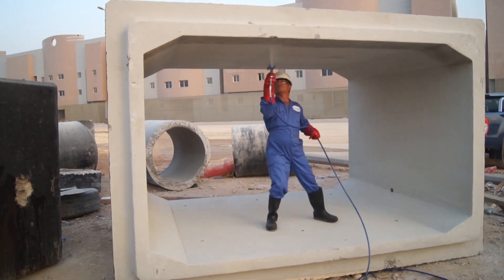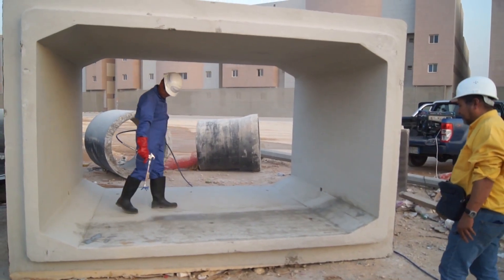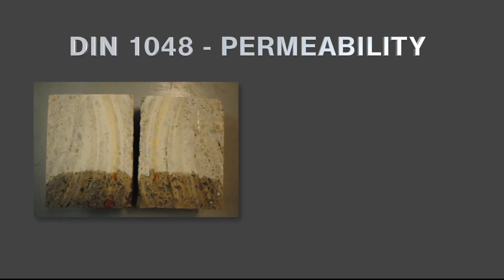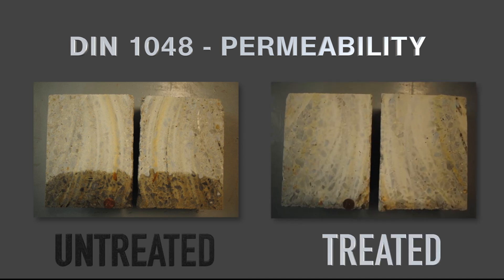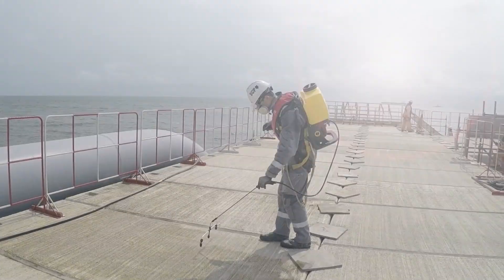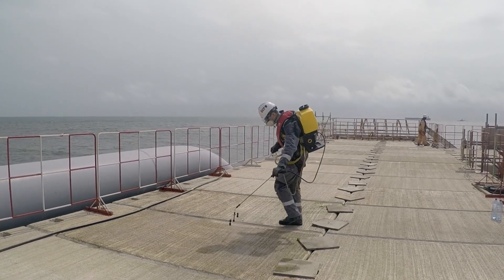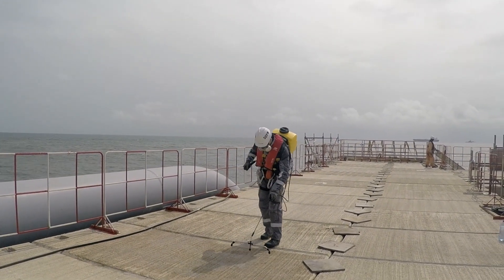Spray Lock has been used on walls where up to 100 meters of head pressure water exists on the opposite side. This internationally accepted test puts concrete under high pressure over three days to test resistance to water intrusion. Spray Lock is added to the sample on the right, and you can see the very limited penetration indicated by the size of the penny on it. Spray Lock also provides complete protection from salt attack in marine environments, as the salt can no longer penetrate into the capillaries.